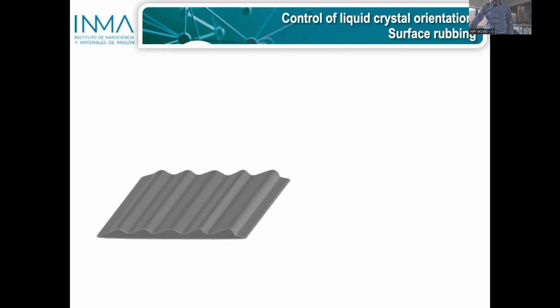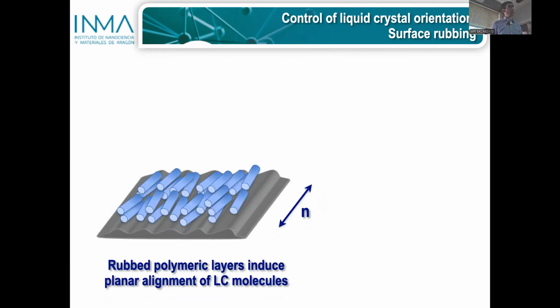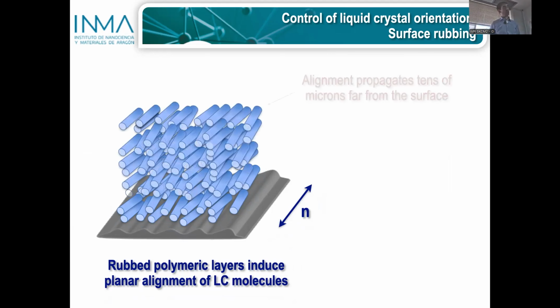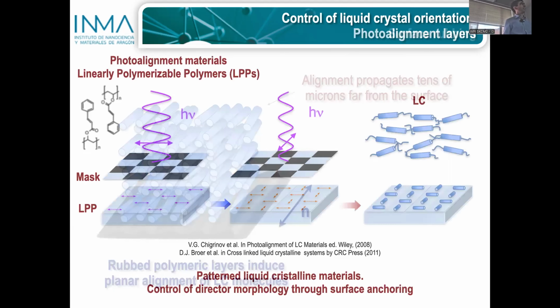You get grooves in the polyimide, and if you put a liquid crystal on top, the molecules close to the surface will get aligned parallel to the grooves, and due to the elastic character of the liquid crystal, this alignment will propagate far away from the surface, typically on the order of tens of microns. Above tens of microns, there is a limitation. The liquid crystal order is lost and is driven by other factors. It will not follow the orientation of the substrate anymore. So this, as we will see, will be a limitation in our case.